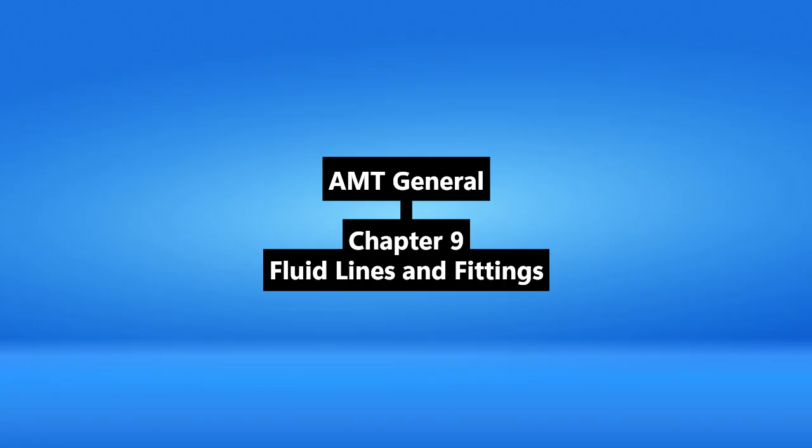Okay, let's shift gears to flexible hose lines. Used where things move, vibrate, or need flexibility. Exactly. Connect moving parts to stationary ones, absorb vibration. Connect metal tubes sometimes. Modern ones use synthetics, not just rubber. Like Buna N, neoprene, Teflon. Yeah, Buna N for petroleum fluids, butyl for Skydrol, EPDM. Critically important to match the hose material to the fluid. Wrong combo leads to failure.